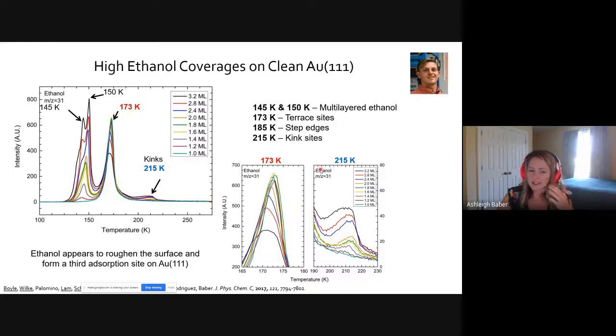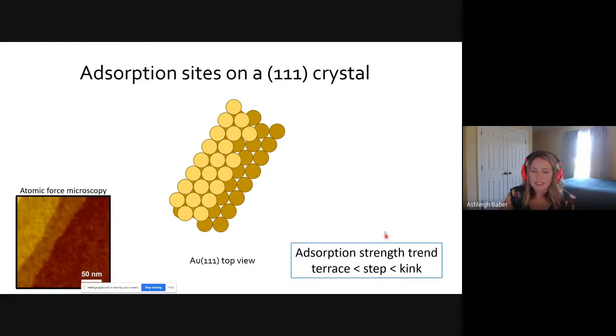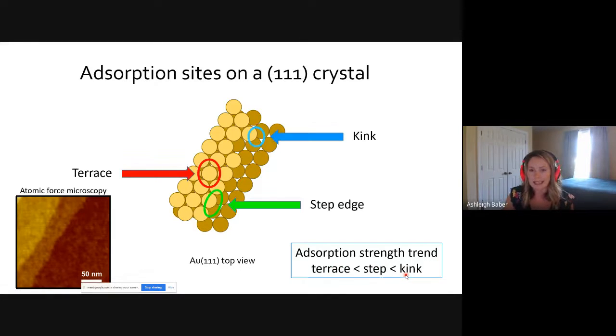And so this is a study that we published several years ago now, but this is something that we want to return to and look at through a DFT lens as well. So in summary of this section, we can look at the adsorption strength trend. And as you expect, we can see that ethanol is bonded to terraces more weakly than step edges, and that's more weakly than kink sites. This is going to be really important when we start to think about intermolecular interactions as well.